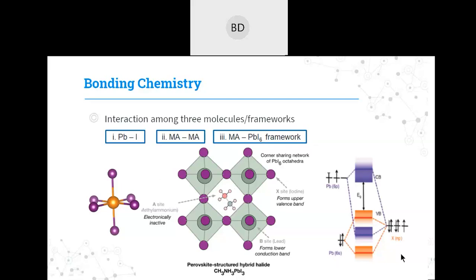If you see the band structure of the perovskite, the valence band is contributed by the hybridization of the 6s orbitals of lead and the p orbitals of the halogen, whereas the conduction band is contributed by the unoccupied, empty 6p orbitals of lead. So the A side cation is electronically inactive. It doesn't contribute to the band structure of the perovskite, but it plays a very important role in changing the band gap. If you change the rotation of this methyl ammonium, or give it a little tilt, it will affect the overall perovskite structure. And if the structure is affected, its symmetry will change. Once you change the symmetry of the structure, obviously the band gap is going to change. So it is not electronically active, but it has a very important role in governing the band gap of the perovskite.